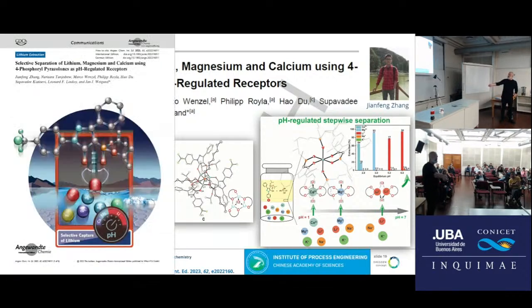And so we've done this on the cover. You have here the pH, so it's like, you know, these little machines where you put a coin and then you maneuver and then you get the iPhone, or you get the 100,000 bill or whatever, or you get just like a puppy out of cotton, or nothing. And so here you really adjust what's going to be taken out by adjusting the corresponding pH. I think that was very fascinating for us, because now you can be much more sustainable without adjusting the pH too high, being selective for lithium. And that's a much, much better, in our opinion, interesting approach towards the separation and recovery of lithium.